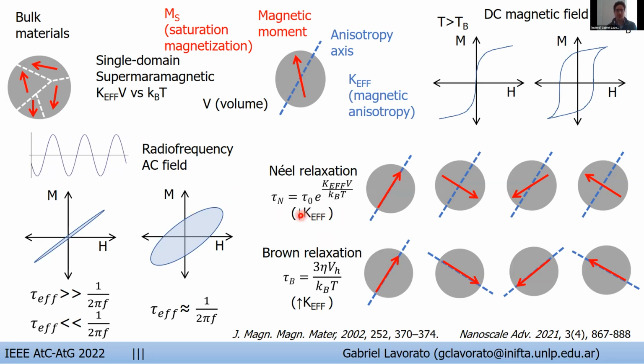Two heating mechanisms associated to relaxation processes with different characteristic times are usually considered. A Néel process, which is effective for particles with low anisotropies and is due to the rotation of the magnetic moment within the nanoparticles, and also a Brown process, where the magnetic moment is fixed at the anisotropy axis, promoting the physical rotation of the nanoparticles, which is more likely to occur for particles with large anisotropies. According to this simple model that captures the fundamental ideas of magnetic heating, the amount of energy dissipated by the system depends on the synchronization between the field frequency and the effective relaxation times.